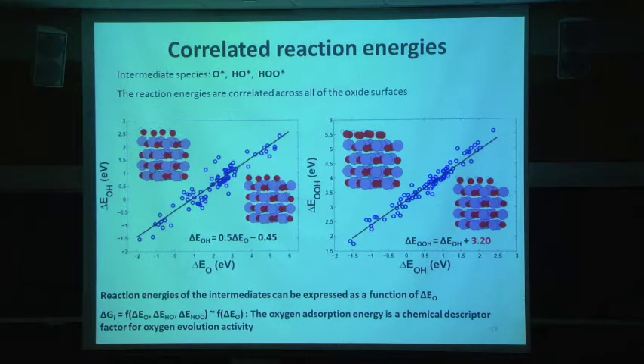So we only have 1 degree of freedom. The binding energy of oxygen in this case corresponds, each one of these is one of those oxides that I showed you. And as soon as you pick an oxide, you determine all the other steps. So that means we can describe, rather than all 4 steps, we can just define 1 step, and everything else is proportional to it. And so either one of these or a difference between this and this becomes a chemical descriptor for the reactivity of that metal oxide.